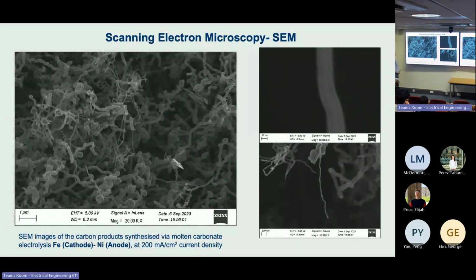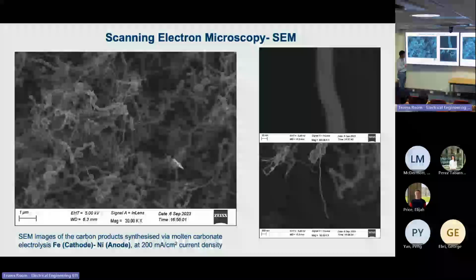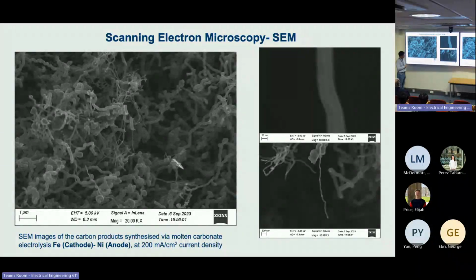Here is the SEM image of the carbon product synthesized via our method, molten carbonate solid electrolysis, using the iron as the cathode and the nickel as the anode. The initial current density was 200 milliamps per square centimeter.